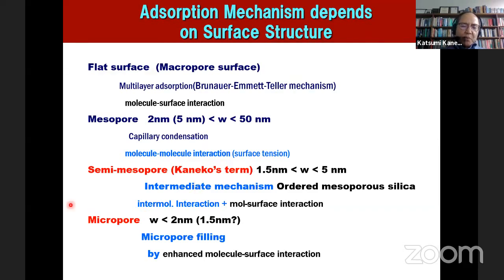But the a little bit smaller mesopores, 5 nanometers to 1.5 nanometers, and little bit larger micropores, often show very unique adsorption behavior, because in this case the molecule-surface interaction is important and also the molecule-molecule interaction is important. Then these materials are still being studied by many scientists from a fundamental viewpoint. And the representative adsorption is so-called micropore filling. Adsorption starts from very, very low pressure, just applicable to smaller micropores, possibly less than 1.5 nanometers. This comes from the enhanced molecule-surface interaction, which I mentioned before.